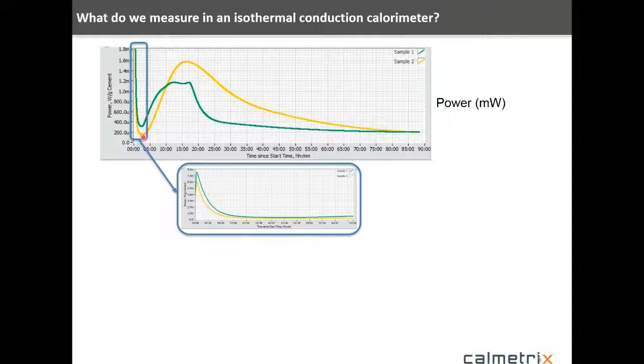I've blown up the beginning portion of this curve, which illustrates the point that when you drop a sample into the calorimeter, the sample is never at the same temperature as the calorimeter, so there is a time associated with the sample coming into equilibrium with the environment in the calorimeter. And that might take a couple hours, depending on the mass of the sample and the heat capacity and so forth. So you just have to bear that in mind from an experimental design standpoint and from a data interpretation standpoint, and realize that these startup events are going to happen at the beginning of the experiment.